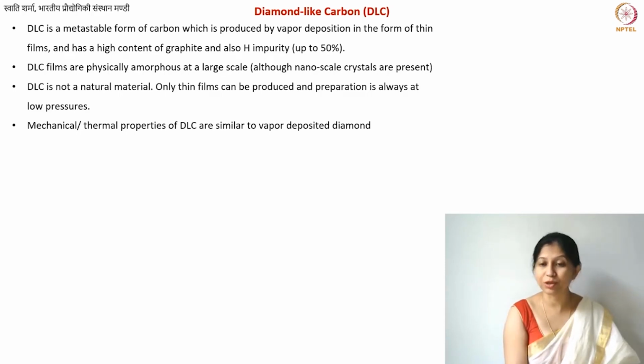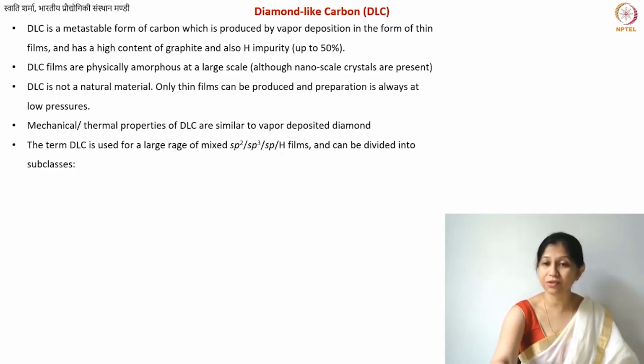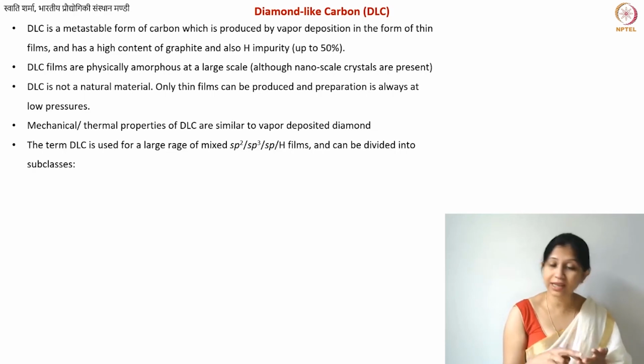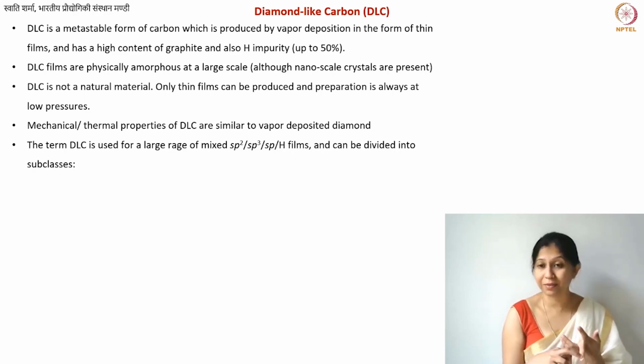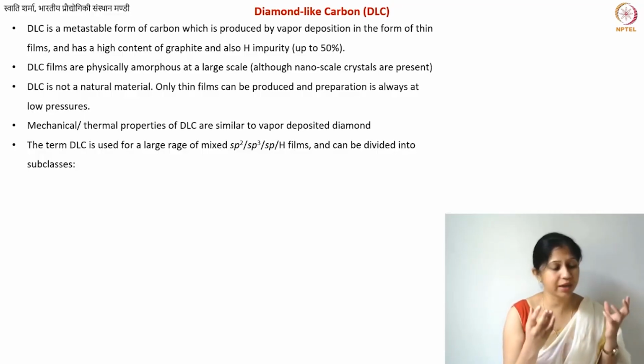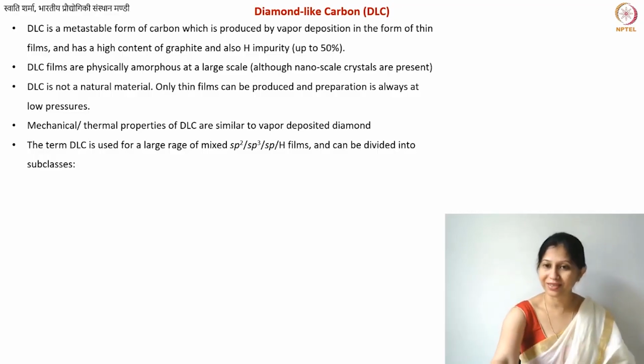So as I said, this is not a natural material, and the mechanical and thermal properties of this material are very similar to vapor deposited diamond, and that is why we use this for a lot of technological applications. What you have in DLC is sp2, sp3, hydrogen, as well as sometimes sp hybridized carbon. So this is basically a mixture of all types of carbons, but you do have a reasonable amount of sp3 carbon present, unlike in the case of disordered carbons or sometimes carbon fibers, where you have